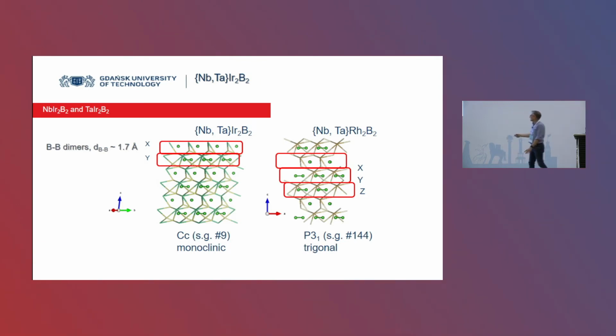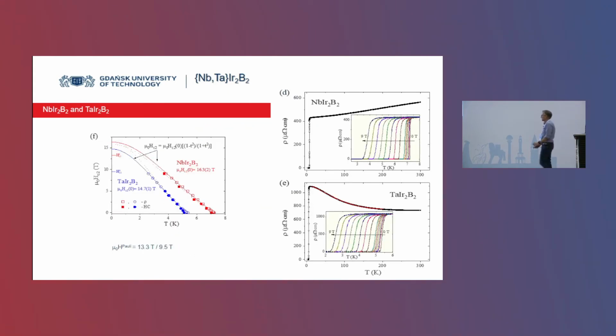Both are superconductors, and they have very similar superconducting properties. Now, let's go to physics. So first is resistivity. And you can see that there is a clear transition. Great. So there is a transition to the superconducting state. Then we plotted the upper critical field as a function of temperature. And of course, we finished at 9 Tesla. I will show you more points in a minute. Nevertheless, the upper critical field you can obtain from WHH theory, it's about what? About 16 Tesla, which is way above the Pauli limit.